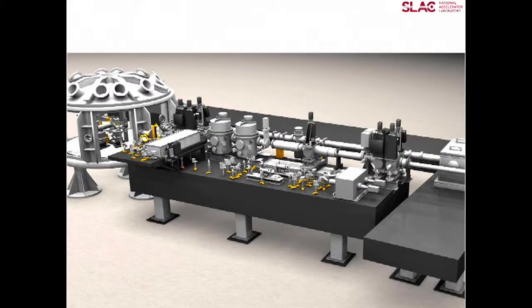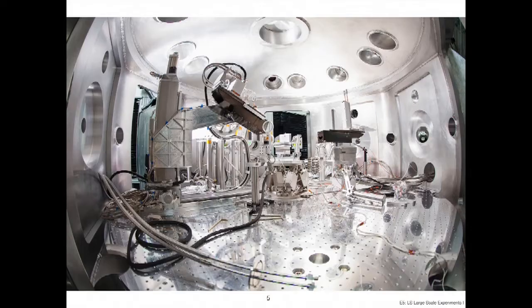We have a big vacuum chamber where all our experiments take place. The X-rays come in through this X-ray tube. There are some X-ray diagnostics to qualify them. We have a couple of optical diagnostics on the outside that are used to measure the strength of shock waves and the motion of surfaces of materials. But most of our diagnostics actually sit in this big experimental chamber, which is a vacuum chamber with a diameter of 2 meters.